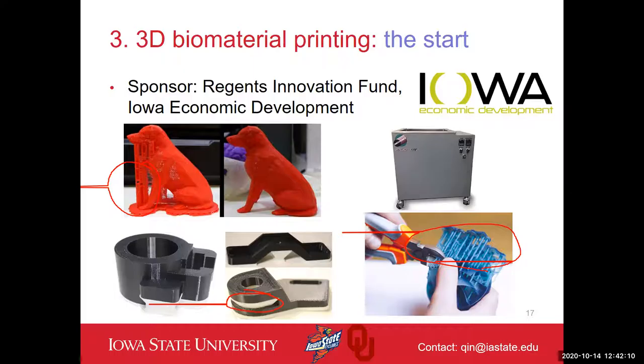What we are trying to do is figure out ways to better handle the supporting materials and structures. Currently, those supporting materials either have to be broken off by a tool, or we have to put the material into a chemical solution tank to dissolve the supporting material. That's not environment friendly. So my idea was how can we develop new materials so that we can use water to wash the supporting material away, without having to put it into a chemical solution or use mechanical force to remove it? Mechanical force may possibly jeopardize the printed structure.